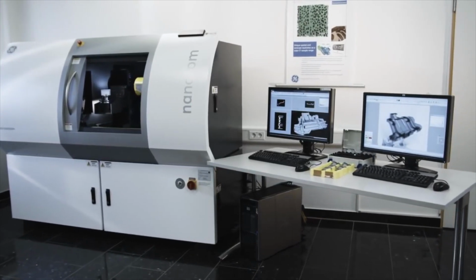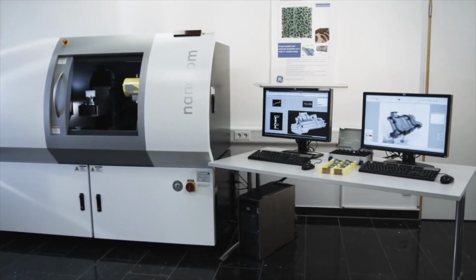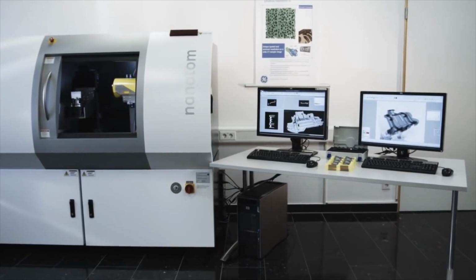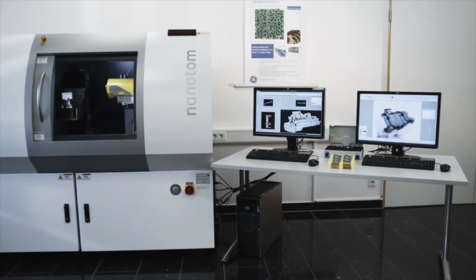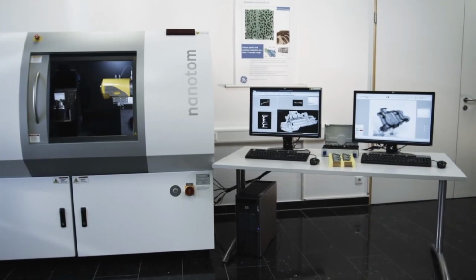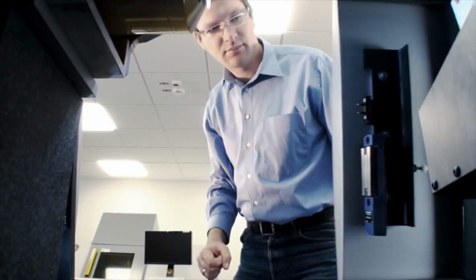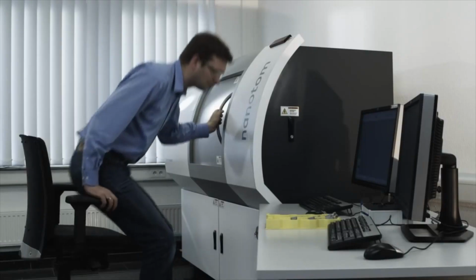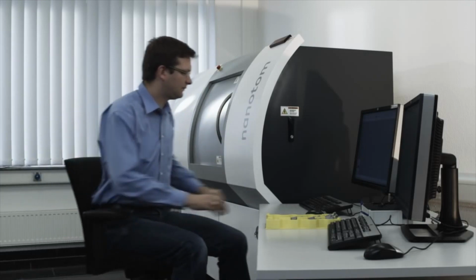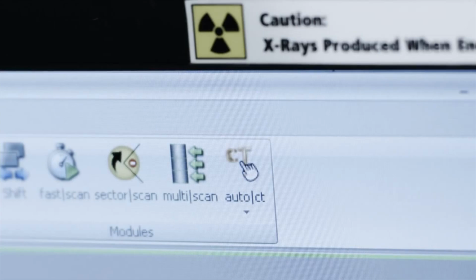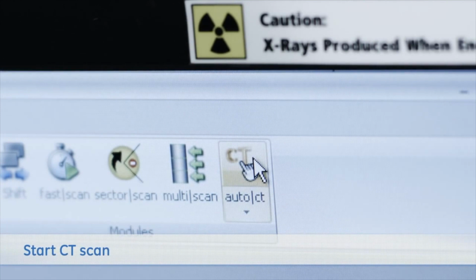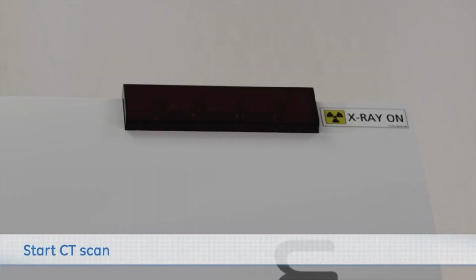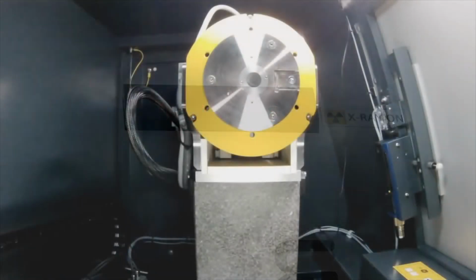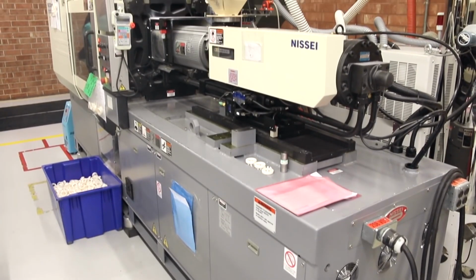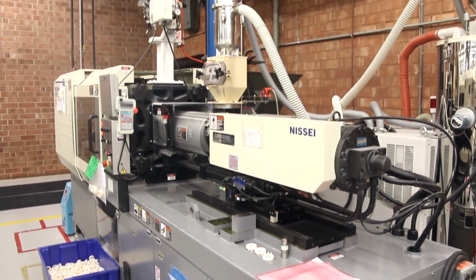To quantify the dispersion quality, structural analysis was made on the tomography images. There are numerous values that were measured, including structural model index that indicates the presence of structures, the structural thickness, the structural separation, the linear density. The author presented the results in a graph that compared the two types of compounds. Another comparative graph was made with the total porosity of granules that were produced with and without ventilation. The graph presented the results that the porosity percentage was higher with ventilation than without.